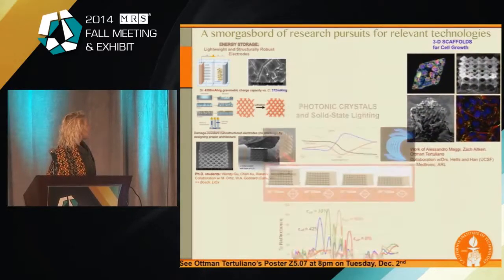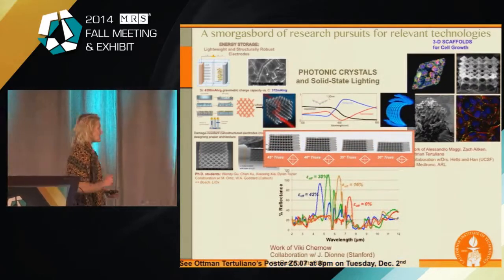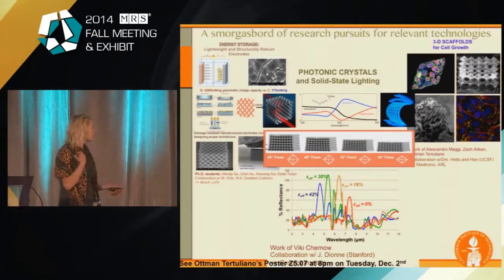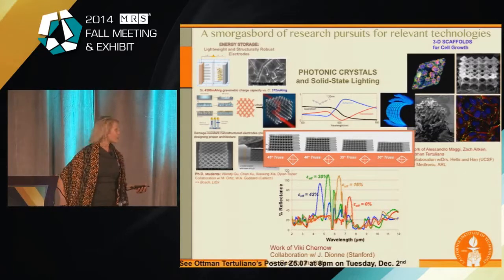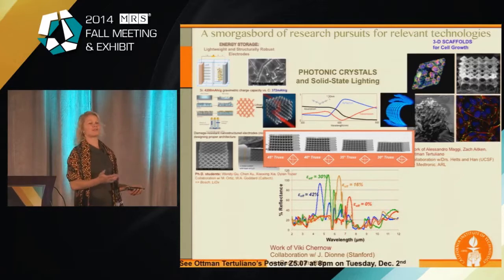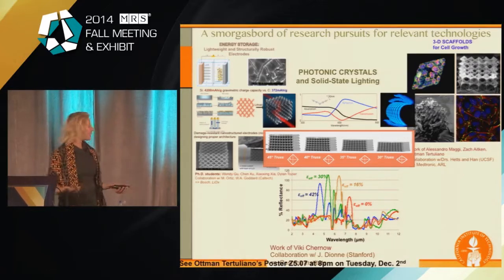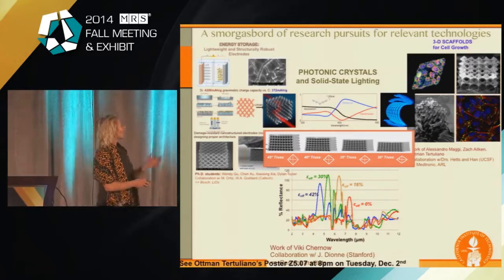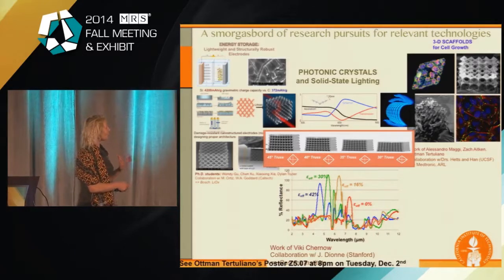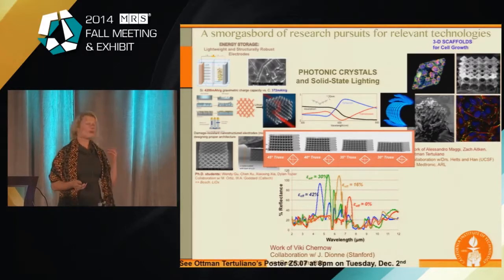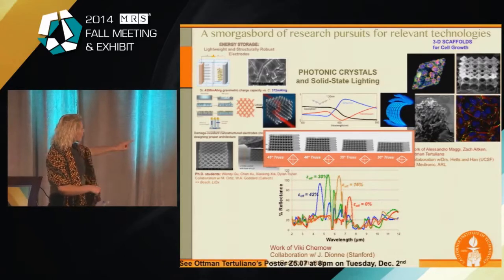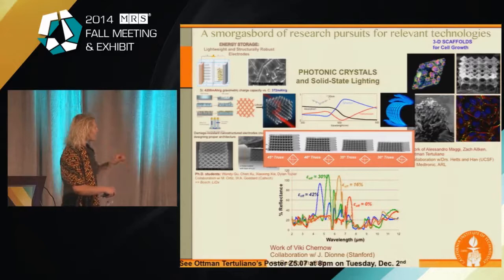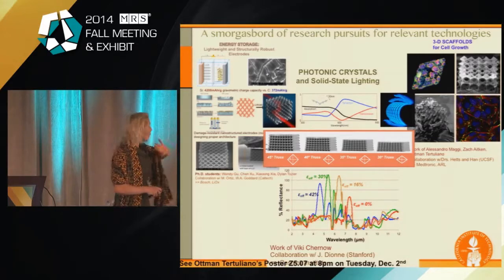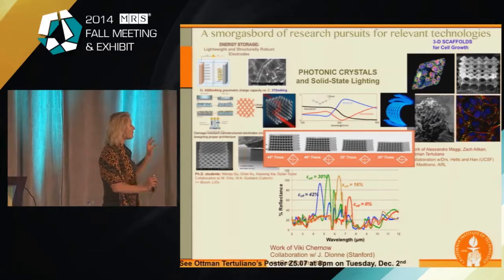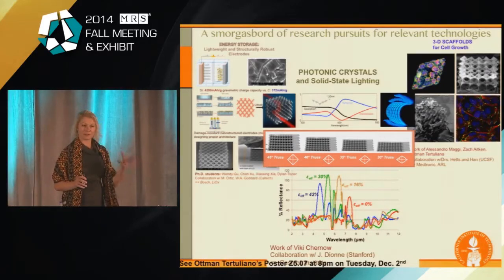Now, these are periodic nanolattices, and I work at Caltech, where we effectively can only major in physics, and specifically in applied optics. So everybody who goes to Caltech pretty much majors in physics and then just gets a degree with a material science flavor or biology flavor or something like that. So we work with a lot of applied physicists, and of course the periodicity in these structures excited several of them, because they're effectively three-dimensional photonic crystals. And so what my student Vicky showed is that these structures are able to exhibit a photonic band gap. These are polymer structures, and all the coupling into light and the interactions with light come simply from the geometry. Nothing to do with the size effect. This is simply from the geometry.